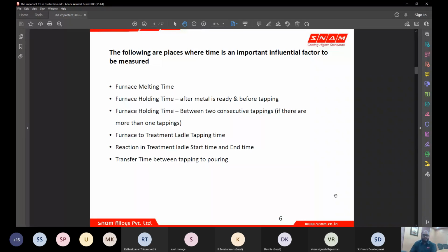And next comes the furnace holding. After you have completed your melt, that means your liquid metal is ready to be tapped, you go into the phase called holding. Most foundries do not hold the metal, as they are well aware that holding increases their energy cost and reduces their nucleation potential, and it may lead to various defects. It can be a slag related defect, with more slag getting generated, or a structural defect from less nucleation potential, demanding more inoculation and maybe leading to remote location shrinkages, like in thick sections, where you can get a lot of shrinkage. So that is the furnace holding time.